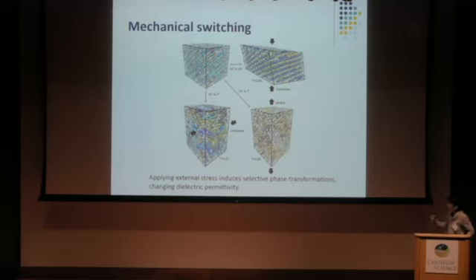First we prepare the antiferroelectric phase in equilibrium and apply external stress in some directions, and we found that in the top case, antiferroelectric to another antiferroelectric phase with different particle orientation is realized. In another case, an antiferroelectric to ferroelectric transformation, and in the third case, an antiferroelectric to paraelectric transformation is found. So this implies the interesting possibility of controlling the phase by mechanical stress.